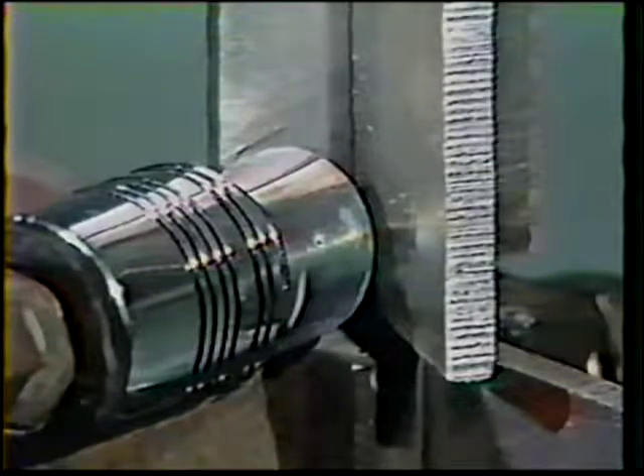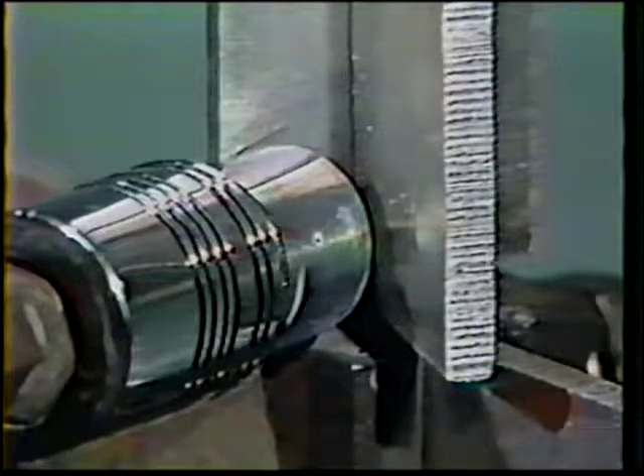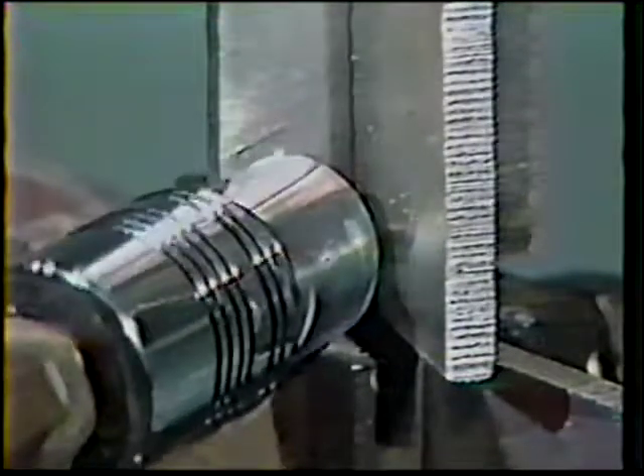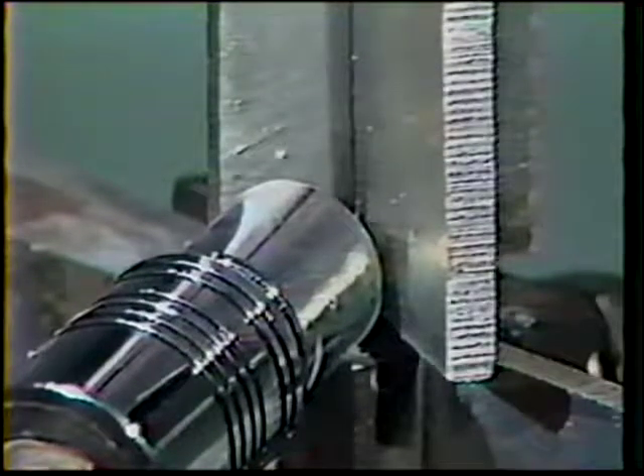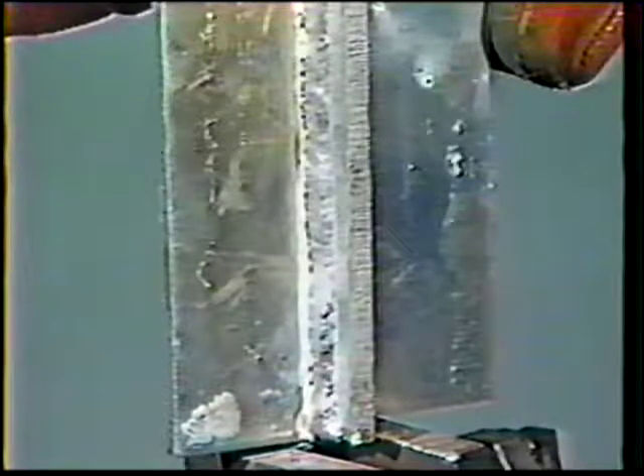Position the gun at the bottom of the joint with a 45-degree work angle, centering the wire in the joint, and a 5 to 10-degree push travel angle. Start the arc and adjust your travel speed so that the electrode wire is melting off just slightly ahead of the center of the puddle. Do not use any weaving motion. The finished bead face should be 3/8 inch wide and flat or slightly convex.